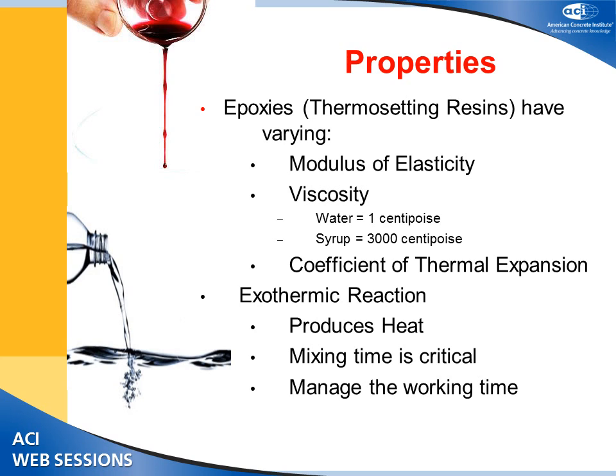To refresh our memories, the viscosity of water is about 1 centipoise and the viscosity of syrup is 3,000 centipoise. This is relevant because the thinner the epoxy, the more likely it will penetrate fine cracks — so for crack injection, we should use thin epoxies, depending on the application. Epoxies are also exothermic reactions — they produce heat — so mixing time is critical and you must manage the working time allowed.